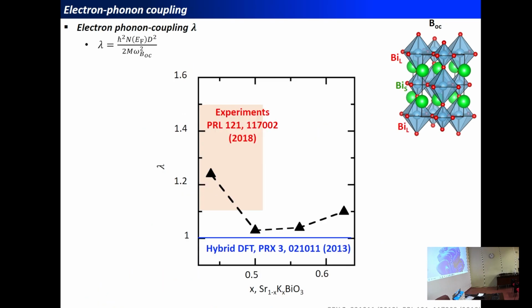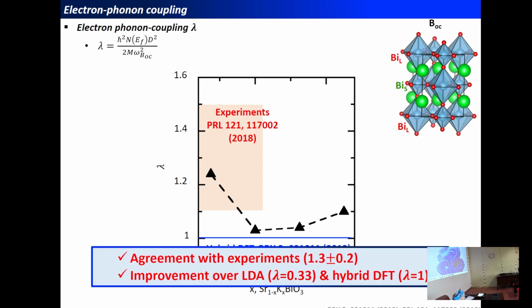And so we have all the terms we need to compute the electron-phonon coupling lambda in this system. And so if we do that across the different doping content, we end up with a lambda which has the highest value around 1.22, decreasing a little bit when we put more holes and becoming constant. And this value is in very, very good agreement with the experimental report, which is around 1.3 plus minus 0.2. So we are precisely in the error bar of the experimental measurement in the optimally doped samples. So there are no reports of what's happening in the other doping contents.